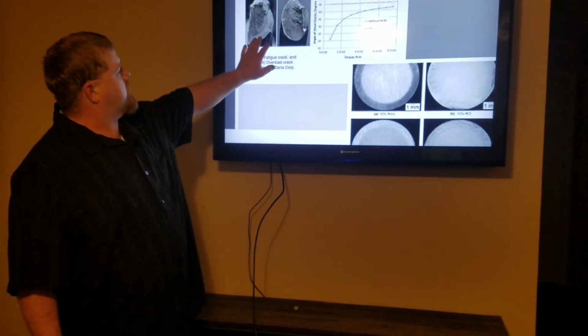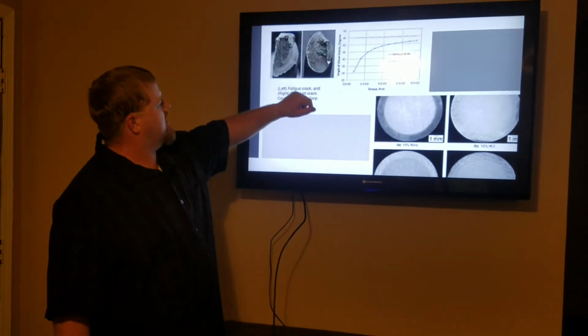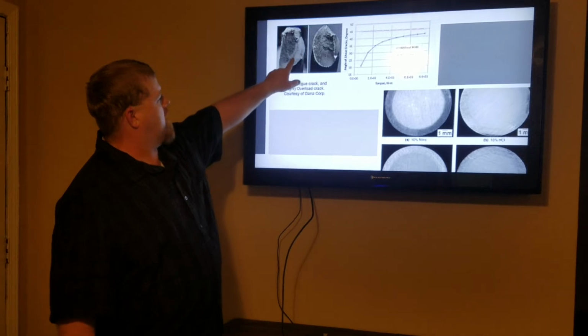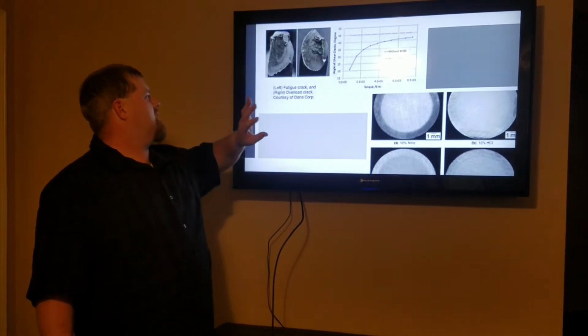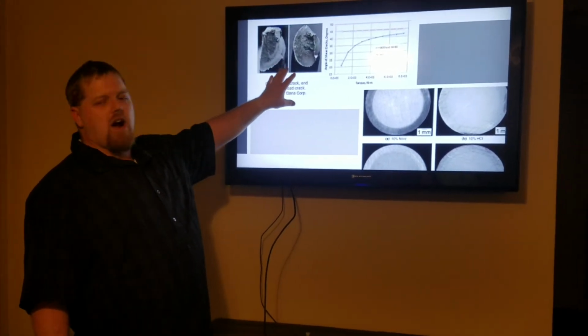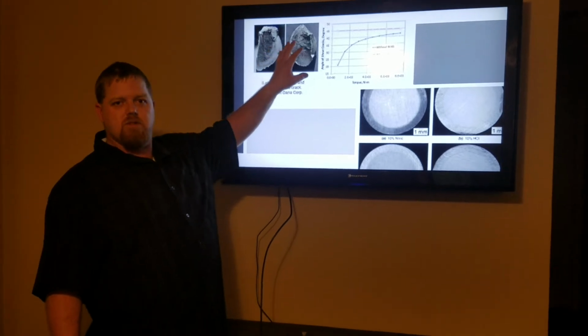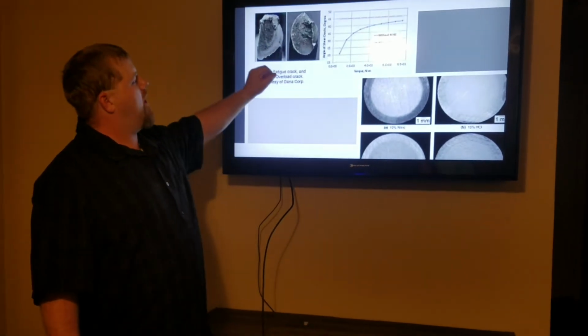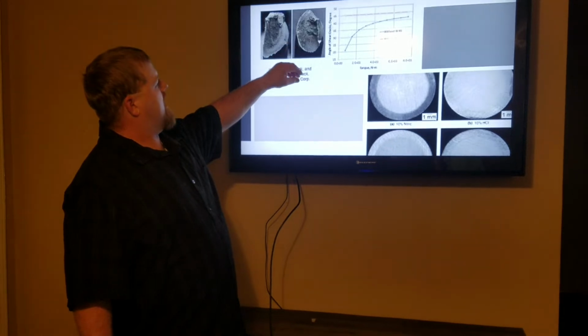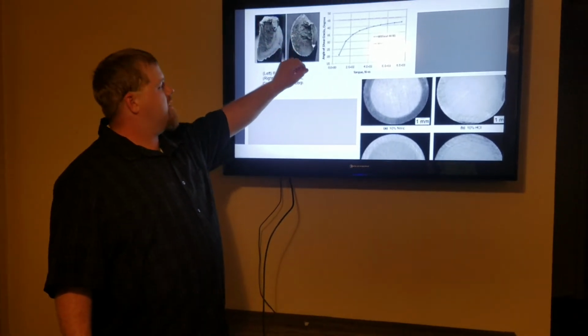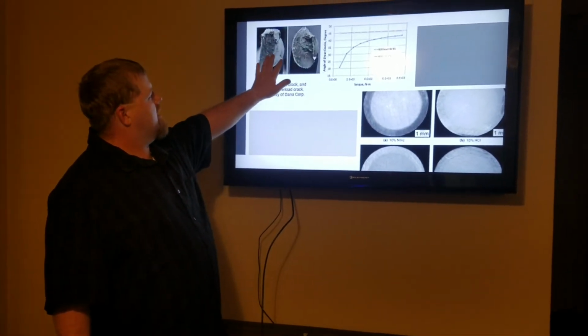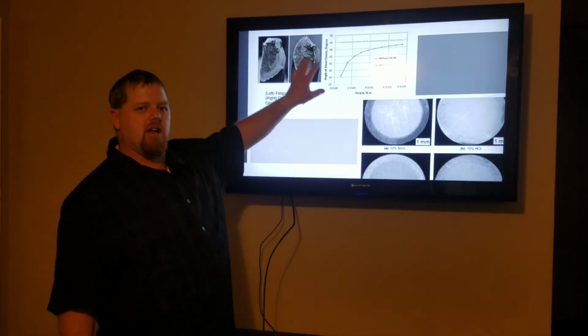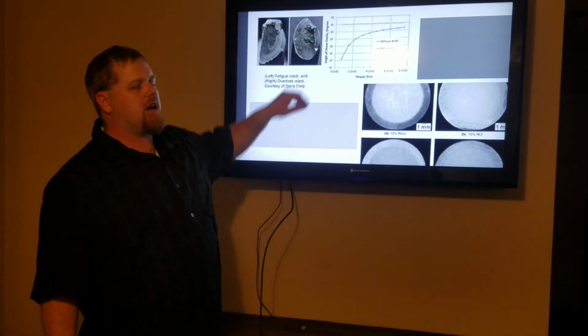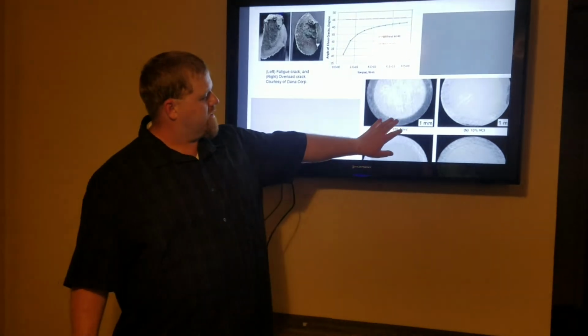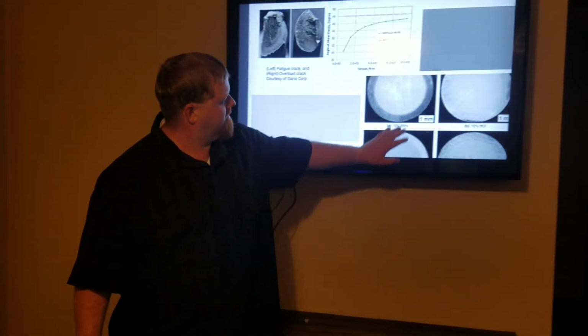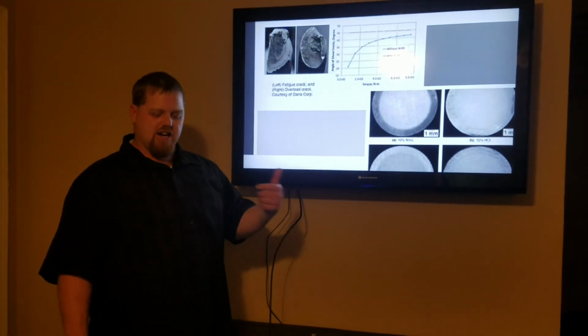So this is an example of something that wasn't hardened correctly. As you can see, it broke. It was either cracked from overheating the material, or there's a possibility that they didn't heat treat it enough. But either way, without proper heat treatment and quality in heat treat, you end up cracking parts and having failures in the field. You can see here different views of a case depth and different etching processes.